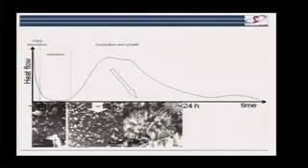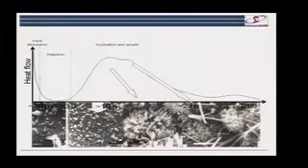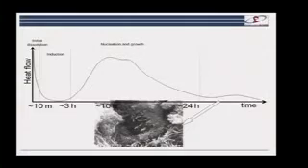Through this acceleration point, this CSH is forming more and more. We come to this point, and it starts slowing down. We're pretty sure now that most of the reason for this slowdown is space being used up. As the CSH from one grain starts to meet up with the CSH from the other grain, there's less space for it to continue forming, and this is why the reaction starts to slow down, but it will still continue. We see this little bump here, which I told you was the secondary formation of ettringite, and we can see these needles of ettringite which form. And then when we have this monosulfate reaction, we start to form these monosulfate plates, as we saw before.